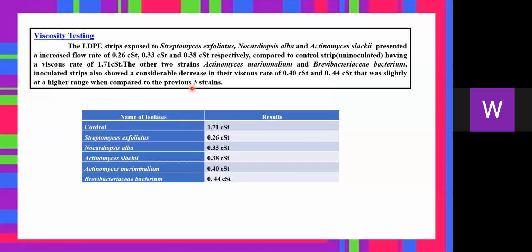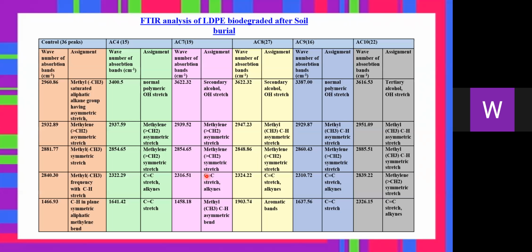Viscosity testing. The LDPE strips exposed to Streptomyces exfoliatus, Nocardiopsis, and Actinomyces slacki presented increased flow rates of 0.26, 0.33, 0.38 respectively, compared to the control strip having a viscosity of 1.71 cSt. Whereas the other 2 strains, mammalium and Brevibacteriaceae bacterium, showed a considerable decrease in viscosity of 0.40 and 0.44 cSt, which was slightly at a higher range compared to the previous 3 strains.